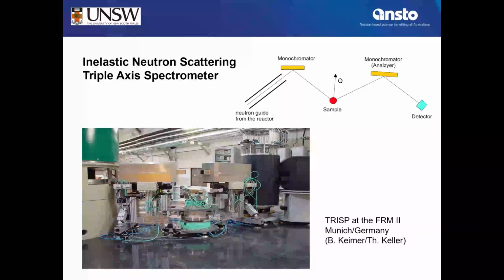So now what happens for magnetic scattering? Unpolarized incoming neutron beam, Heusler crystal, only one spin up component. The sample magnetic signal makes a spin flip down. The scattered neutron passes through the spin flipper and is flipped up again. And now the second Heusler crystal detects that spin-up component.